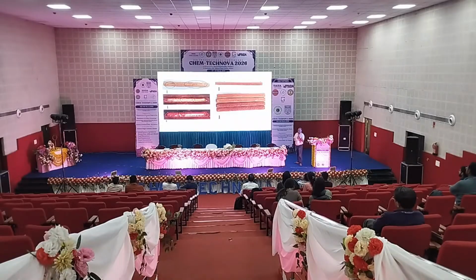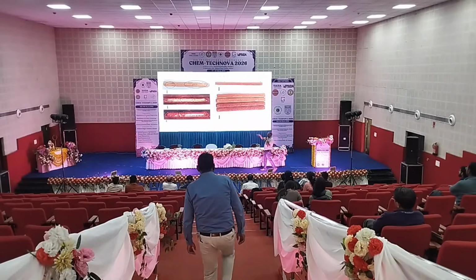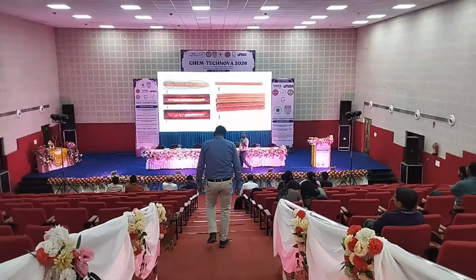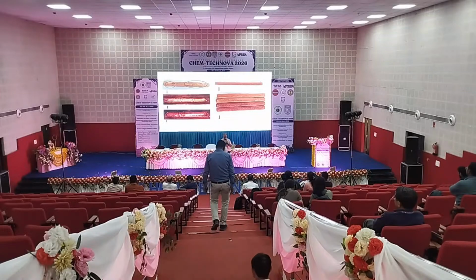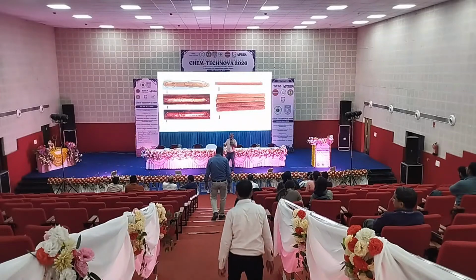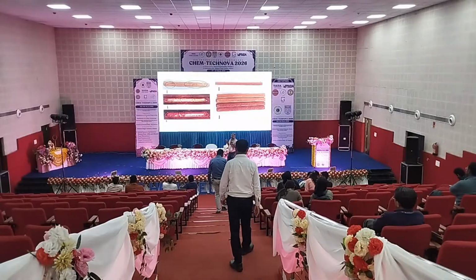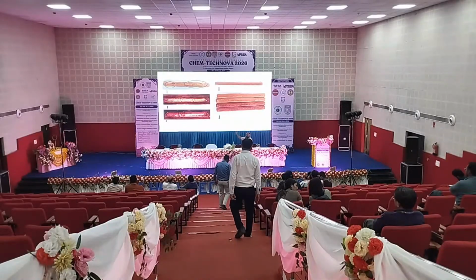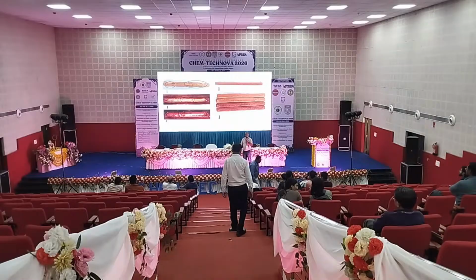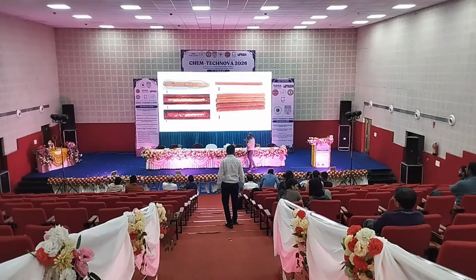Again, I print. So I optimize the printing parameters. I printed. Some of the printing happened, but when I go for the curing, further post curing, I could see that volatiles are getting evaporated, right? So in that way, a lot of cracks happened. It is on post curing. That is also not good. So I should have a proper thing.